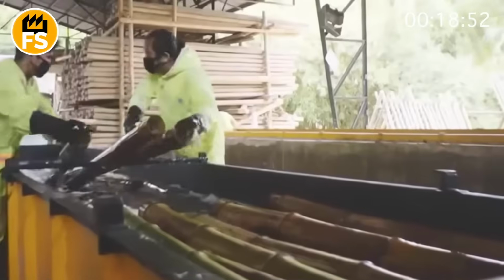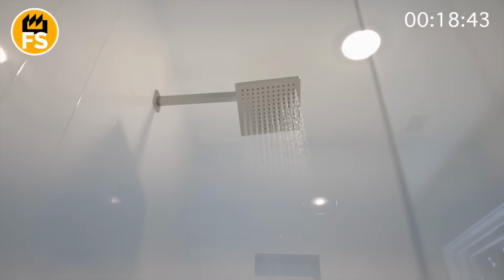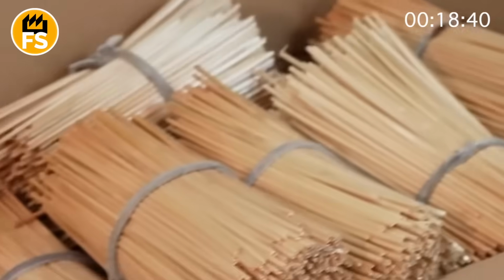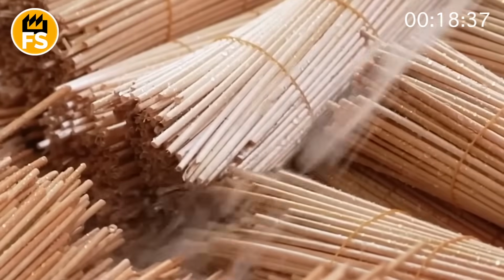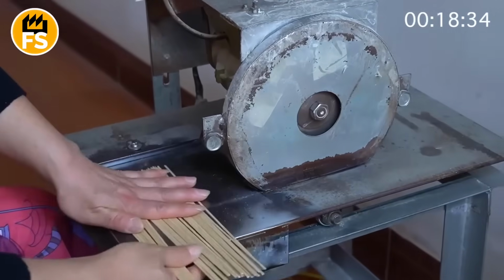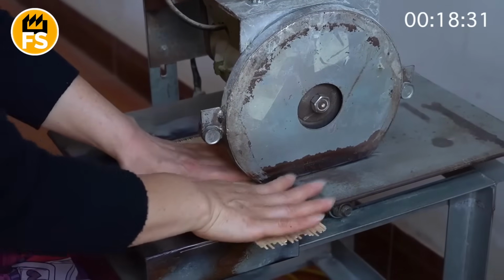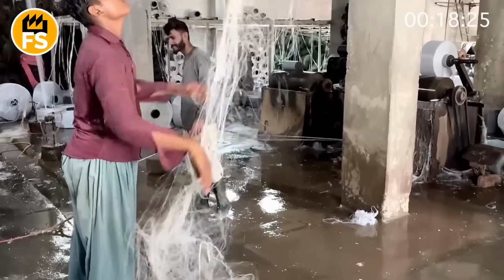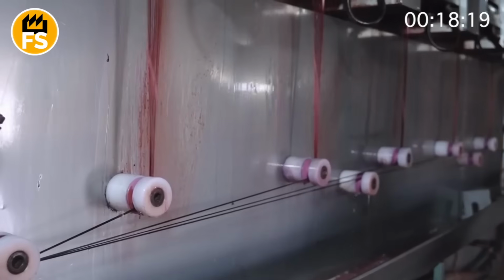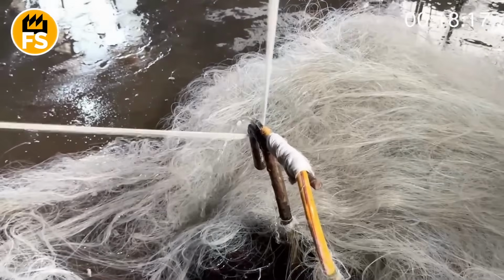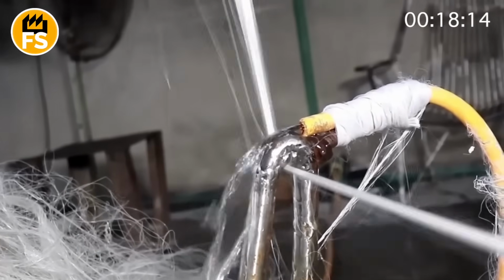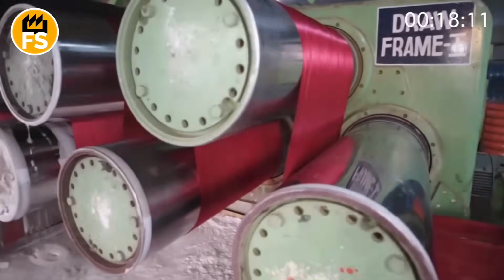viscous liquid. This liquid, resembling honey, is forced under pressure through the finest holes of a metal plate called a spinneret. Imagine a microscopic shower. Emerging from the holes, the thin streams enter a bath of sulfuric acid, where they instantly solidify, turning into endlessly long fibers. These fibers are then washed, bleached, dried, and twisted into yarn, from which fabric is woven. Despite the complex chemical process, the final product is biodegradable and has unique properties. It is extremely soft, hypoallergenic, has natural antibacterial properties, and breathes wonderfully, making it ideal for clothing and bedding.